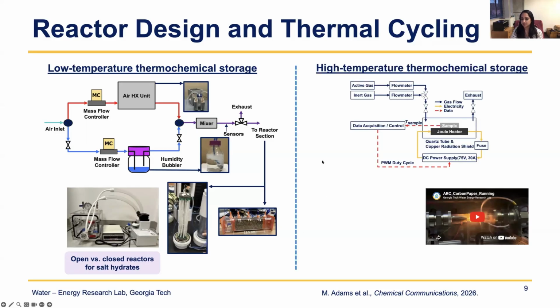For the high temperature systems, we've also developed a capability to do rapid cycling. So we want to cycle from room temperature up to 800 degrees Celsius and do thousands of cycles within a week. So if you do this in a TGA-DSC or in a tube furnace, it will typically take months to get the data for a single sample. So what we're focused on is to develop a way to do 1,000 cycles within 1 week. So heat up the material, cool it down, cycle it thousands of times to study its performance.